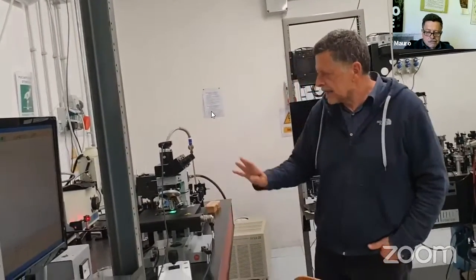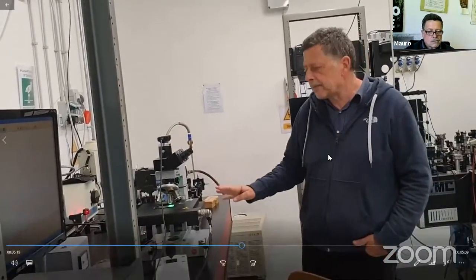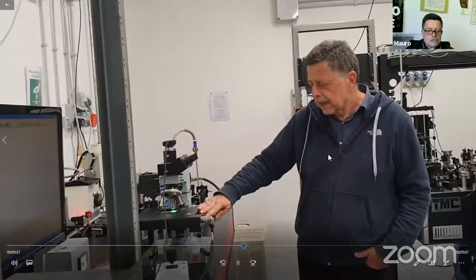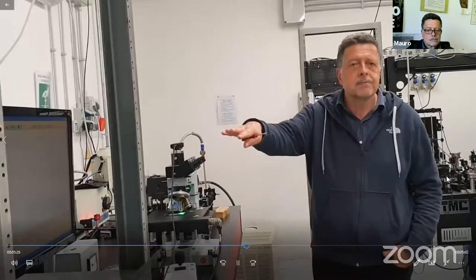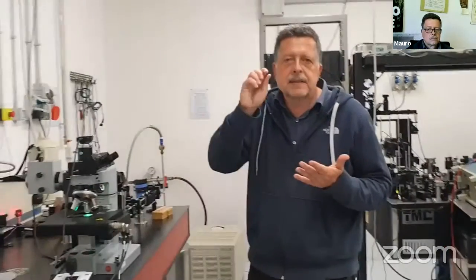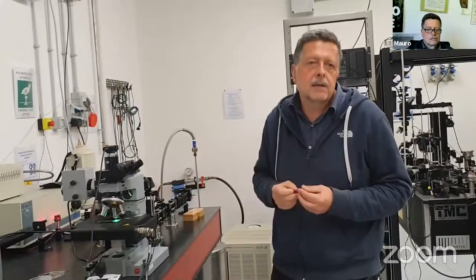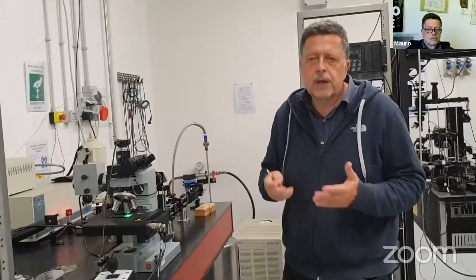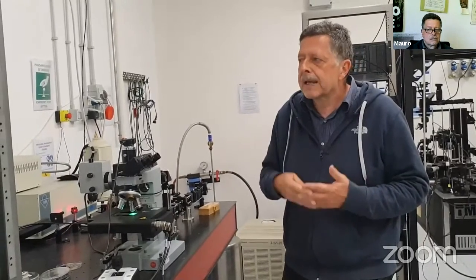Some other features of these experiments are that the sample on the table is controlled by the computer, so that we can make Raman maps in samples which are inhomogeneous. We can map certain bands. We can decide to map the presence of some vibrations. In this way, we have a kind of chemical fingerprinting of the sample.